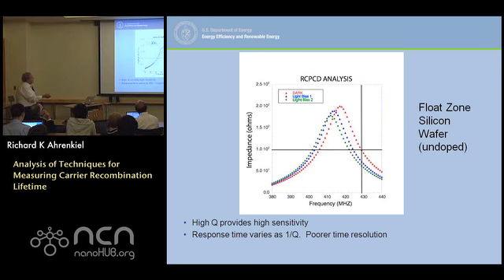So the sample has done this, and here's a sample in the dark. This is float zone silicon. When the sample is in the position that we decided on, the impedance frequency curve looks like this. Now I turn on a microscope illuminator. It changes the conductivity of the sample, so the curve changes to here, and a little more light changes to here. So this is basically the principle of operation. As we increase the conductivity of the sample via light, we shift the resonant frequency to a lower frequency. If we monitor one frequency, say 430 megahertz, and we put on light, we see that the impedance of the entire system changes. And that's the basis of this resonant coupling idea.